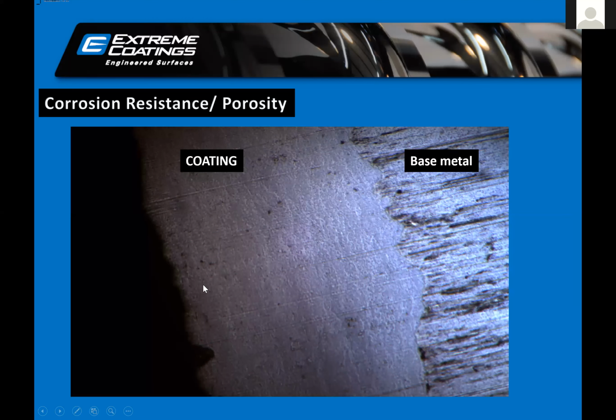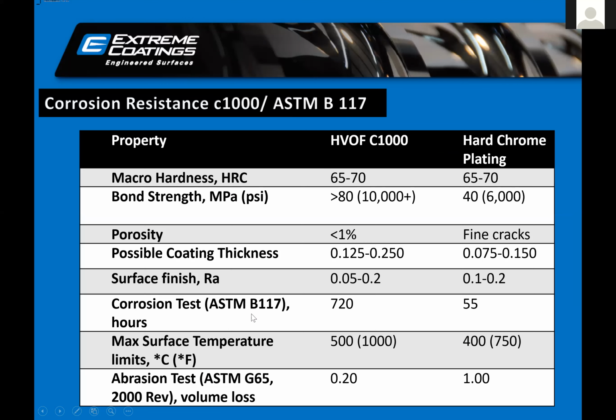Another benefit is the test available in the market, ASTM B117. If I have a coated piece and a chrome plated piece, and we submerge them in an acid tank, within 55 hours the chrome plating is completely gone, while the tungsten coating requires 720 hours. So you can understand the corrosion and wear resistance it has compared to any chrome plating solution.